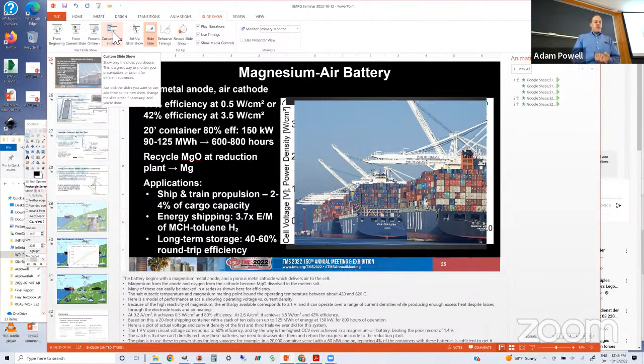One of them is, as you said, just at the end of life, dump out the molten salt, take the magnesium oxide, and send it back to the reduction plant. So that's one option. Another option is, instead of cooling the magnesium oxide side, we heat it so that it dissolves into the molten salt. If we can stay close to the solubility, I think we can get somewhere around 0.1 amps per square centimeter of reduction current density. So we're going to try to reverse the cell and go from dissolved magnesium oxide to magnesium metal.